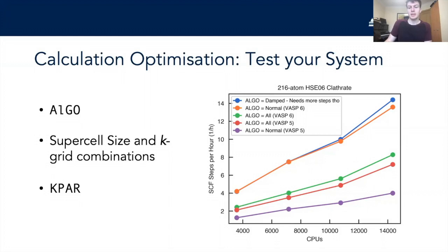You should also consider, as Joe mentioned earlier, different supercell size and k-point grid combinations. It's generally accepted that a supercell larger than about 10 angstrom in each direction is typically big enough to avoid significant elastic or structural interactions between defects, so that our charge correction schemes will account for the rest of the interdefect interactions. So this is another thing to consider when choosing your supercell dimensions.